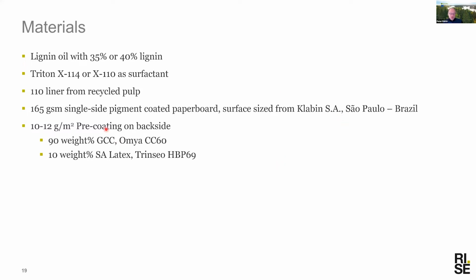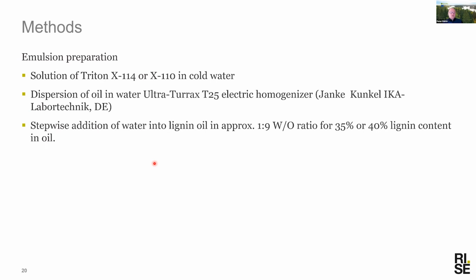And we put it on a liner, and we also put it on a pre-coated board where we used regular paper chemicals. We used calcium carbonate from Omya, a quite common one, and styrene acrylate latex as pre-coating on the backside of the board. We wanted to know what the surface was actually.